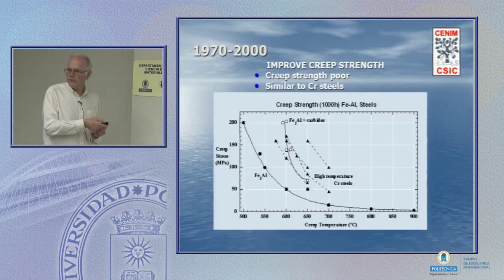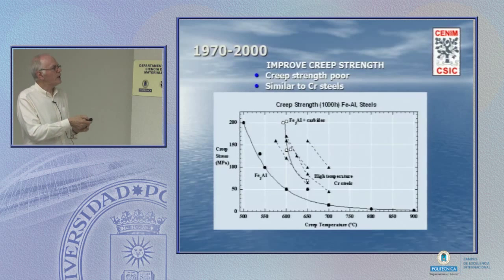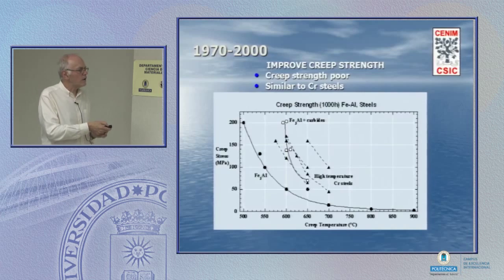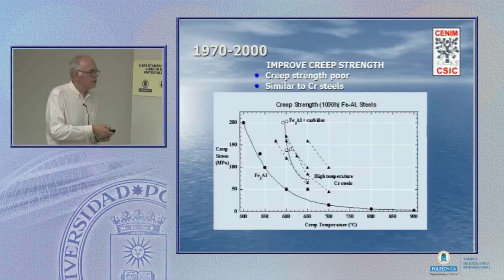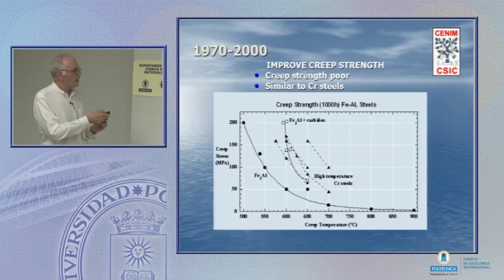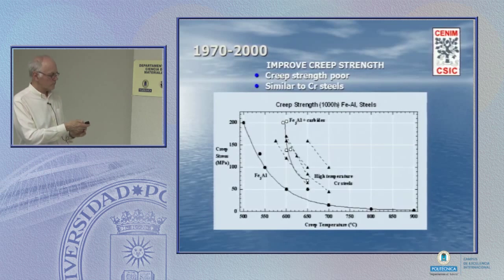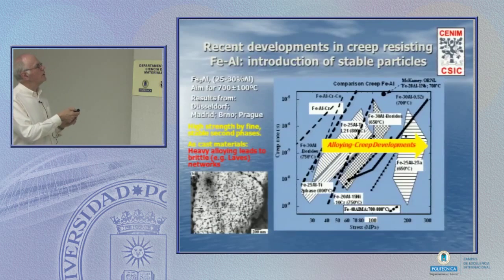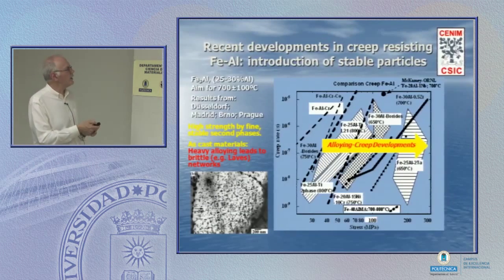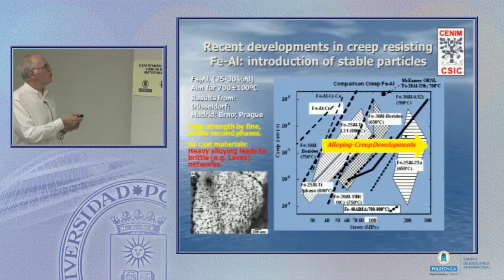And so what do we do with steels? I do exactly the same with the iron aluminides. I add carbides, I add whatever chromium steels, I add whatever obstacle I can to slow dislocation movement. There's a tremendous activity at the moment to try and improve steels that can function in this 600 to 700 temperature range. It's a tremendous problem, and of course the same applies to the iron aluminides. Now, there's been an enormous activity on improving creep resistance of iron aluminides, a lot in Germany, a lot here in Madrid also, and a lot in the Czech Republic.